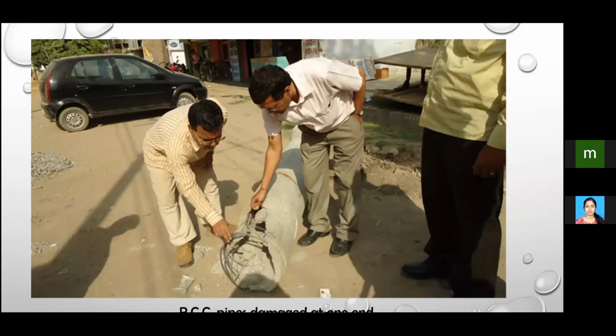Then the RCC pipes damaged at one end. So why did this happen? We took the samples to the laboratory and analyzed, checked that one for strength, and we did the reporting. Okay, and whether the sewer pipe was as per the tender document, as per the contractor's version. So we were checking the reinforcement in a particular pipe; at random, we got this pipe broken, sewer pipes, and we checked the weight.